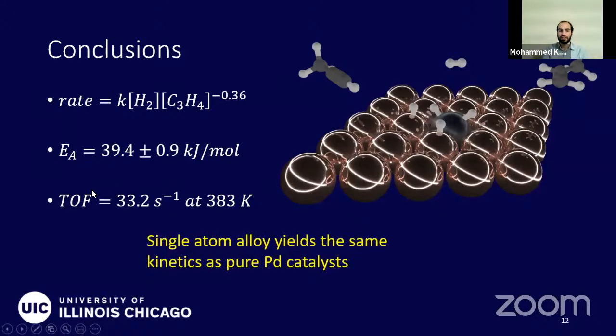And typically in catalysis, we report turnover frequencies or turnover numbers. And we reported here 33.2 turnovers per second at 383 Kelvin. And that's based on palladium being the active site. Whereas some literature will report a lower number using either the whole surface or copper as the active site, depending on where you determine what the rate determining step is. In our case, since hydrogen activation is basically the rate determining step that occurs on the palladium sites, that accounts for our high turnover number.